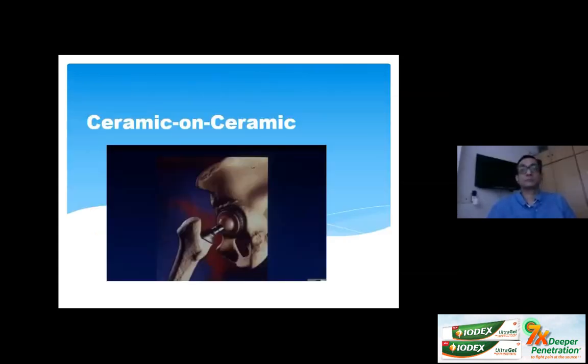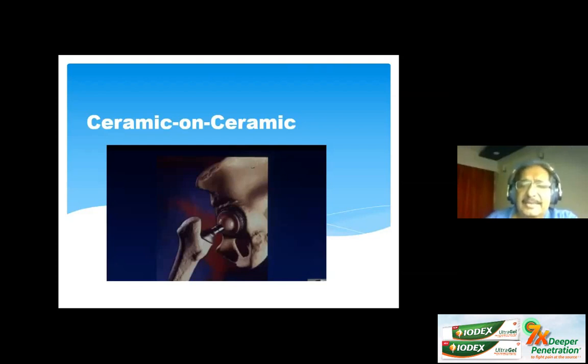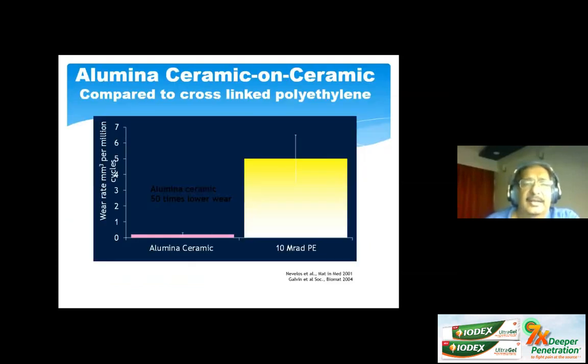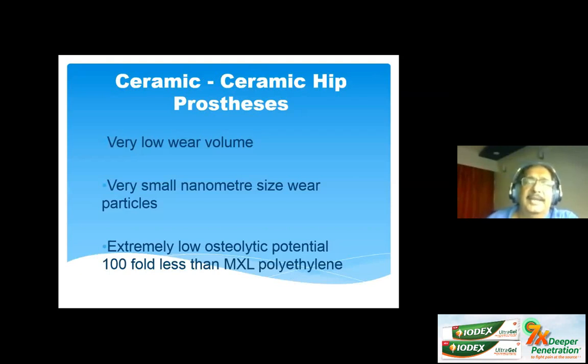What we are using now is more of something called ceramic on ceramic. The ceramics have revolutionized the bearing scenario in hip arthroplasty, where the alumina ceramic shows 50 times lower wear than the moderately cross-linked polyethylene. The ceramic on ceramic hips have very low wear volume. They have very small nanometer size wear particles, and the osteolytic potential is 100-fold less than medium cross-linked, moderately cross-linked, sorry. The ultra-high molecular weight polyethylene fares much better on this score.